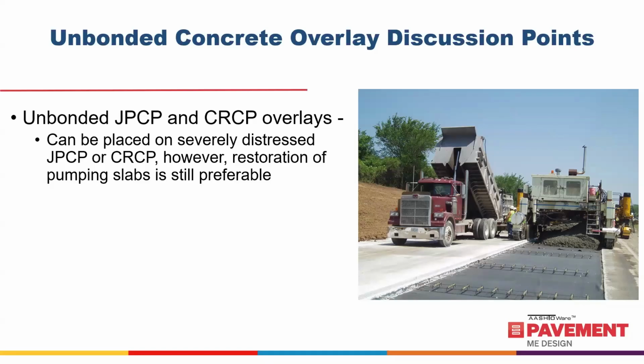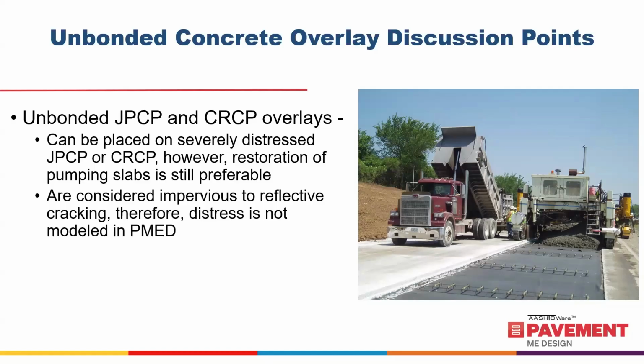But if there's an occasional spot, you can live with that. But continuous pumping problems should really be addressed first, regardless of what strategy you're doing with them. So reflective cracking is not an issue with unbonded concrete overlays because you're more or less designing this as a new pavement on top of a pretty stiff foundation. So you're not anticipating getting reflection cracking. I've never really seen it. I've been around a lot of unbonded concrete overlays in my previous career, and generally that isn't one of the things that afflicted them.